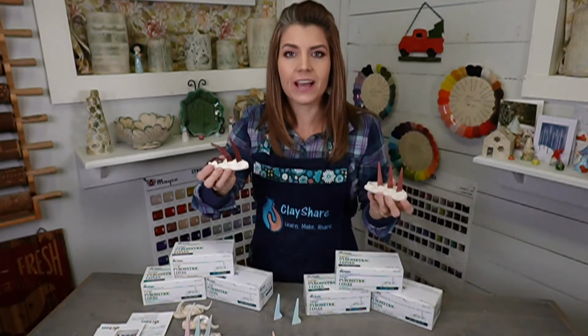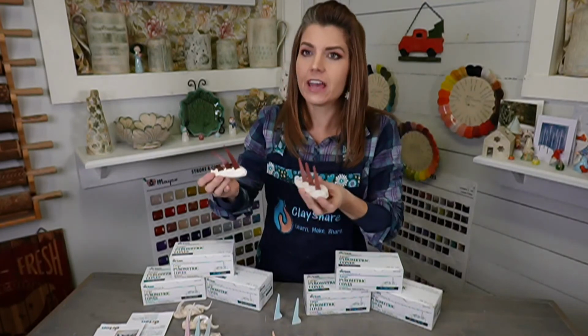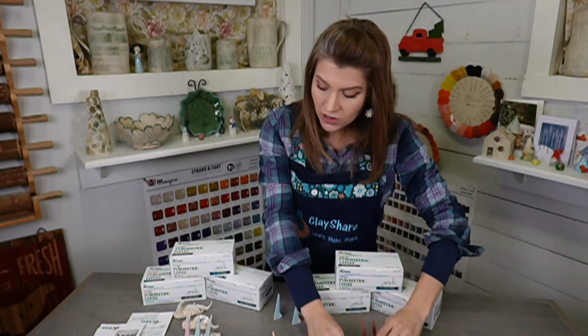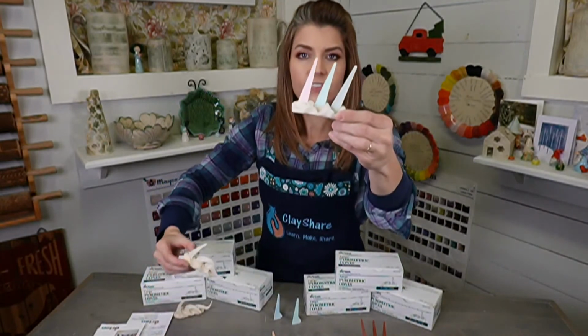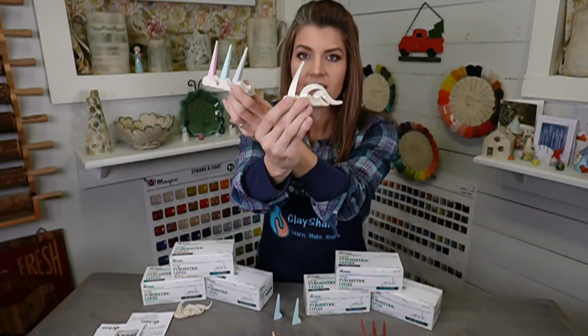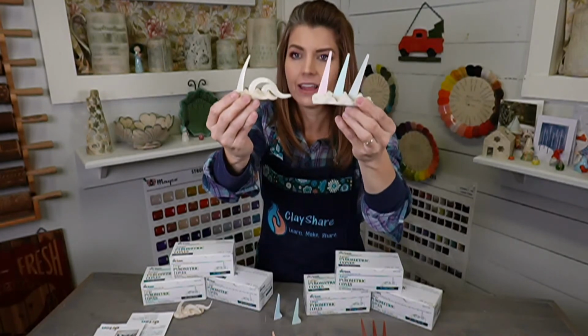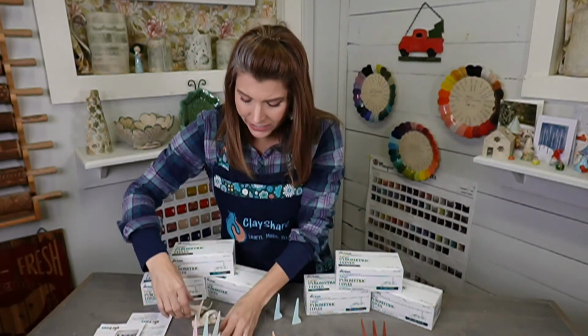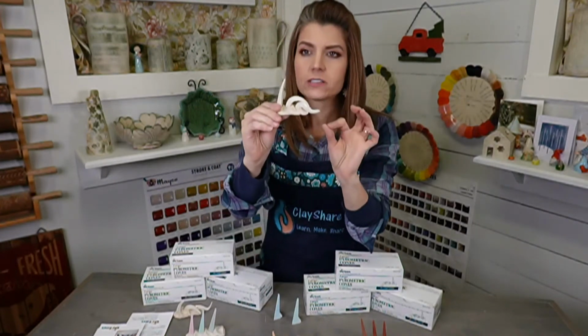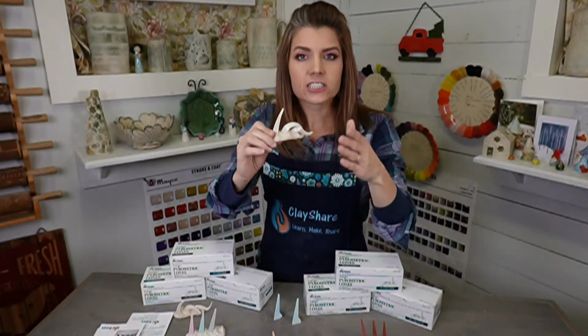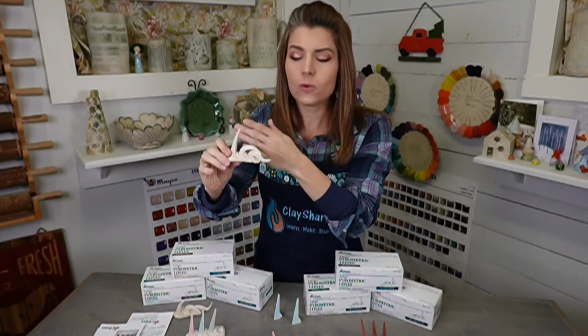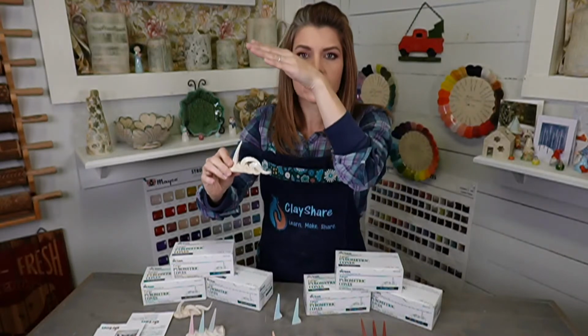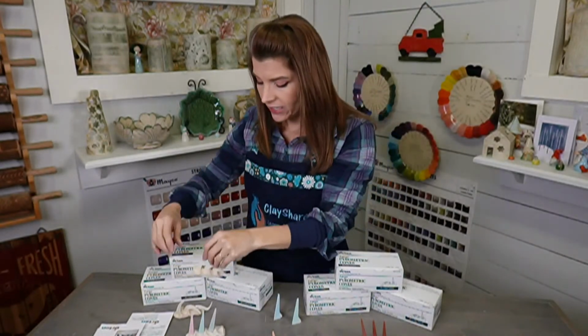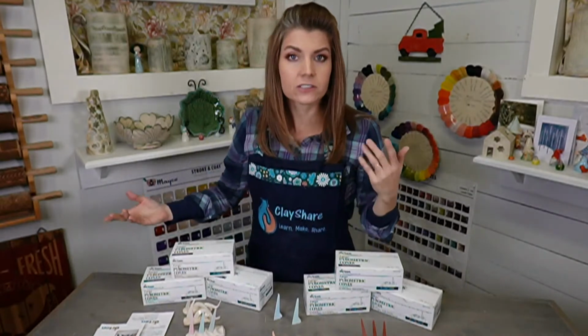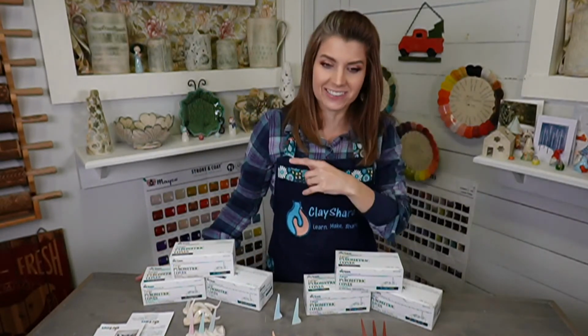And the reason I use the cone packs is I want to make sure my bisque firings are even every time as well. And so for me, I need to track it. And again, here's my glaze firing before, glaze firing after. So this was from my last firing that I did. And so I keep these. I'll keep the finished ones for a little while just to track, usually 3 or 4 firings. I will keep them just to make sure every firing is even. So I can notice if there's a trend where it's going hotter or a trend where it's going cooler. And that really helps me keep my kiln working the best for me so I get the best results.